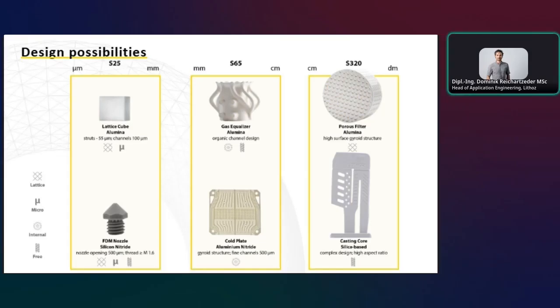Here we can see some examples of what's possible. For example, on the top left, you can see a 3D lattice structure with strut thicknesses down to 55 micrometers and channel size approximately 100 micrometers. Or on the top right, another lattice type part like the porous filter, which is assembled into a 1 meter long filtration system for lithium extraction.